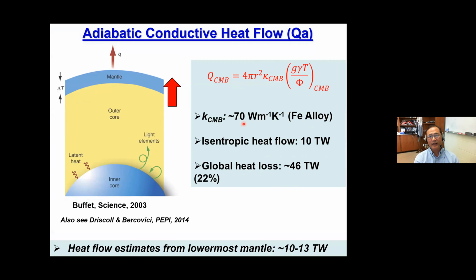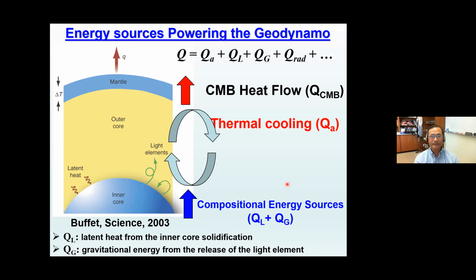So let's just do one exercise here. Let's take this thermal conductivity value K of iron alloy at about 70 watts per meter per Kelvin. And that would actually give us an isentropic heat flow QA of about 10 terawatts. Okay, and again, the global heat loss is somewhere around 46 terawatts.